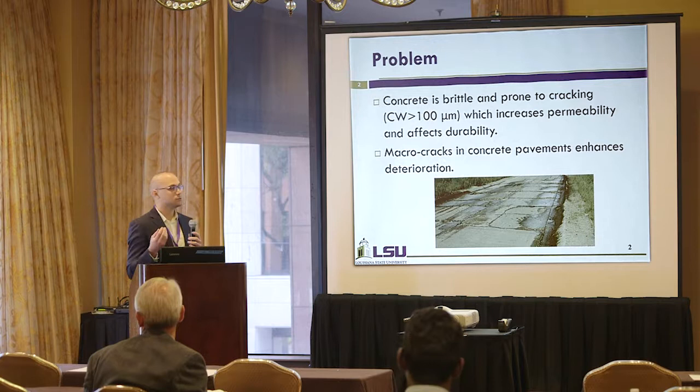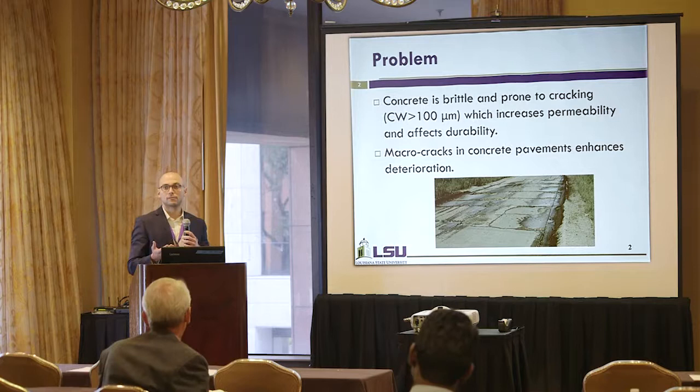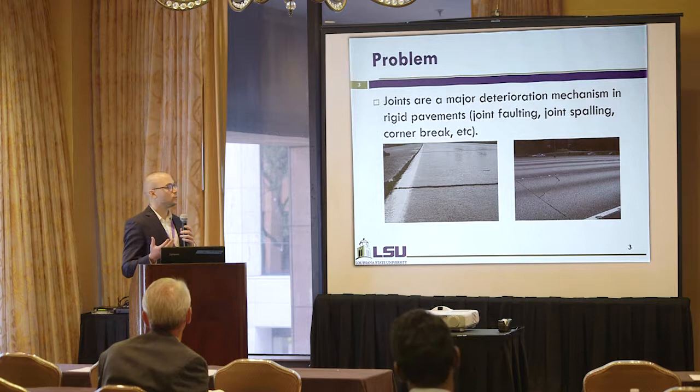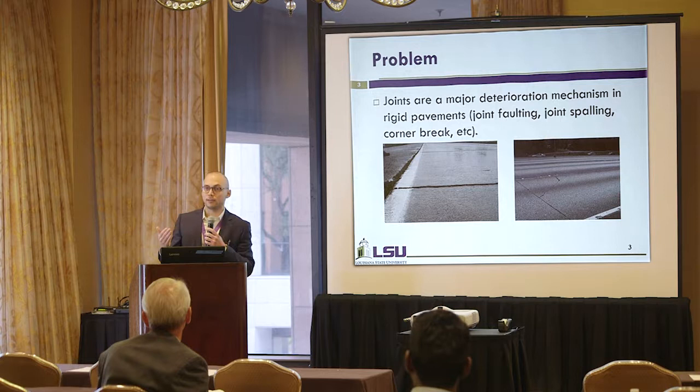The lack of ductility combined with low tensile strength allows cracks to be generated. And what is the problem for pavement when you have cracks? Well, water can go through your pavement and eventually damage your base and sub-base, as shown in this picture. In addition, because of the lack of ductility of concrete, you require joints, and joints are usually one of the main deterioration mechanisms in pavement.